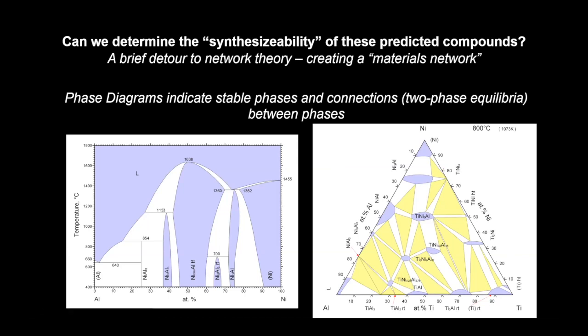Right? Now, the other thing you'll notice about this is that these phase diagrams also tell you what the stable phases are, those indicated in blue, and how these phases are connected to one another in the phase diagram. For example, this phase here is stable, and this one here is stable too, and there's a tie line connecting those two, so there's stable two-phase coexistence between those two phases. But for example, this ternary phase is not connected to this aluminum-rich phase. There's no connection in the phase diagram, meaning that even though these two phases are both themselves stable, if you brought them together in contact, they would not form a stable two-phase mixture, but they would react to form something else.